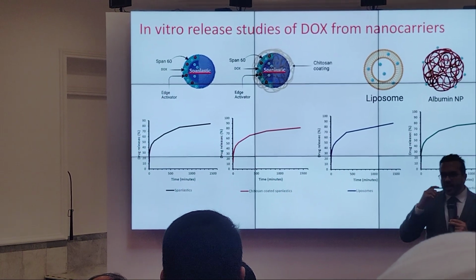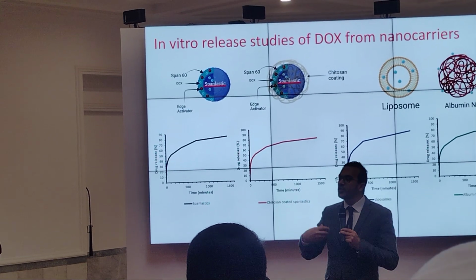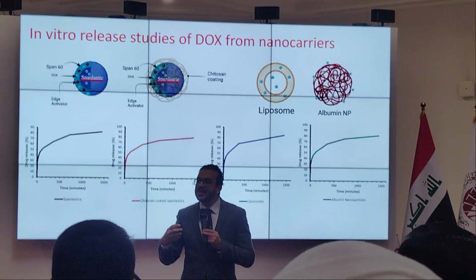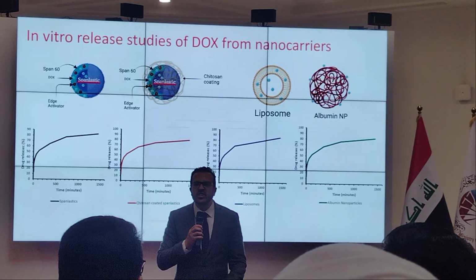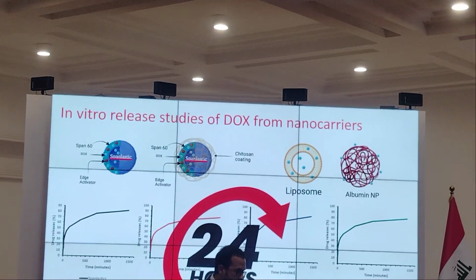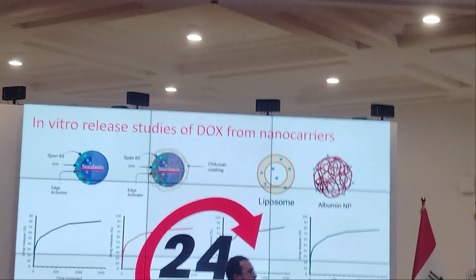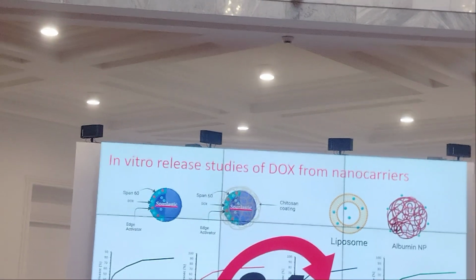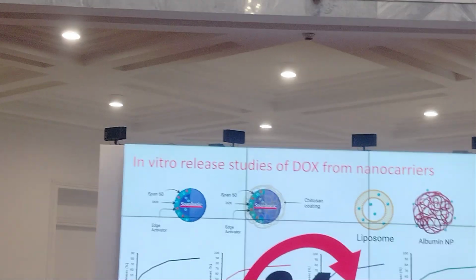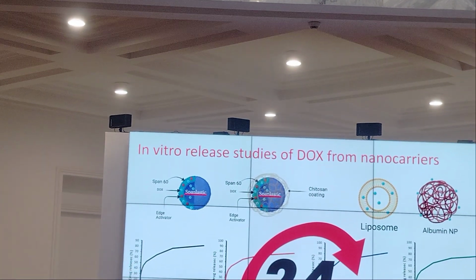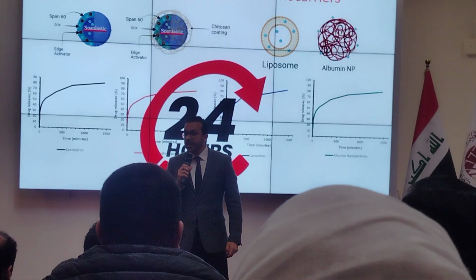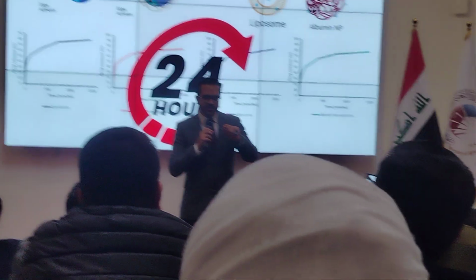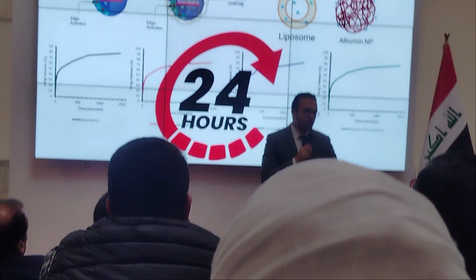One more challenge here is that the release of doxorubicin couldn't be sustained more than 24 hours in all these systems. Do you think 24 hours is enough after surgical operation and implanting this scaffold? So do we need to sustain the doxorubicin only for 24 hours and this will prevent recurrence? I don't think so, right? That's why we have decided to go one more step.